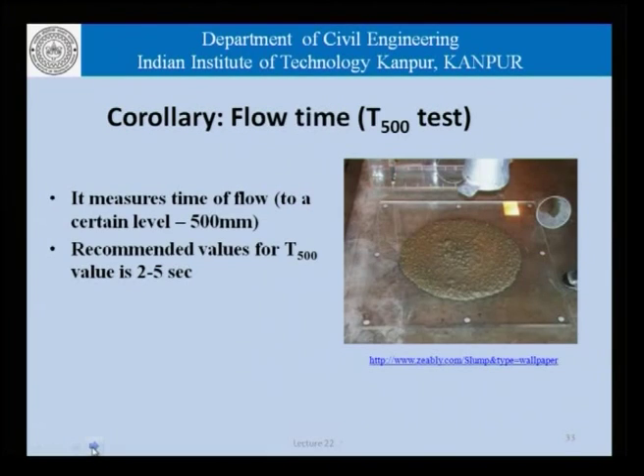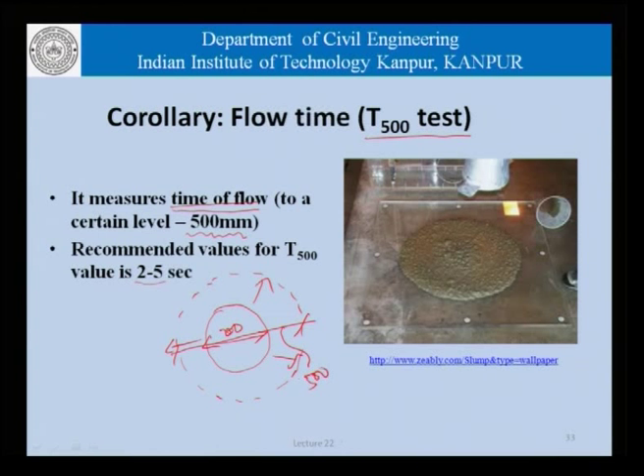As a corollary to the slump flow test, we also sometimes use a flow time, which is sometimes called the T500 test. And now, this T500 refers to the time it takes for a concrete to reach a diameter of 500 millimeters. And the typical time could be in the range of 2 to 5 seconds. So, as the slump cone measuring 200 millimeters in diameter is lifted, the concrete spreads in all directions, and we look at the time that it takes for the concrete to reach a diameter of 500 millimeters, and this time is called the T500.